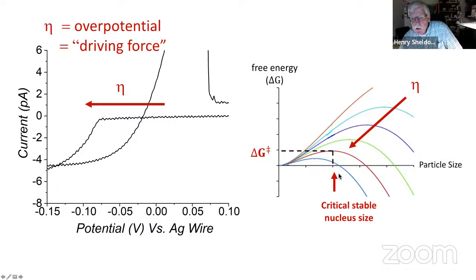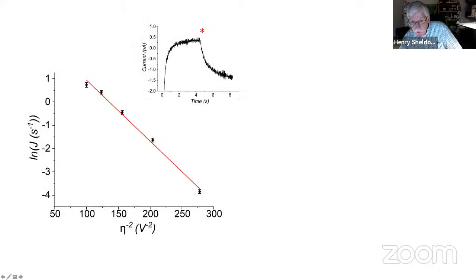All right. The question is, what's the critical size of the nucleus as a function of the electrode potential? And that's what I'm going to tell you about here. So we take these current time traces where we can very precisely measure the nucleation time. This one's at about 4 seconds. And you do that over and over, and you describe the times by a Poisson type process. You can compute a characteristic rate of nucleation.